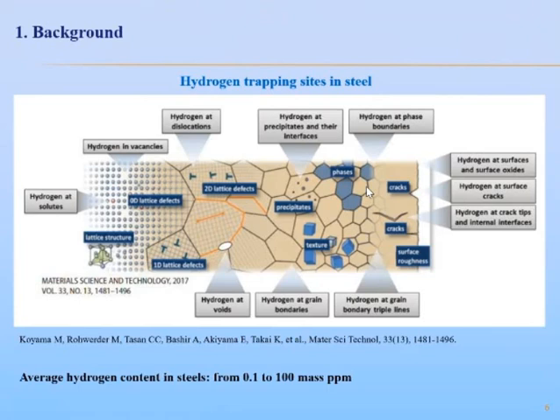Microstructure-specific hydrogen mapping is the most important challenge on the way to a better understanding of the underlying hydrogen mechanisms. Hydrogen is challenging to map due to its low mass, huge embrittling effect already at low concentrations, and a high diffusivity in the presence of compositional, thermal, and mechanical gradients.